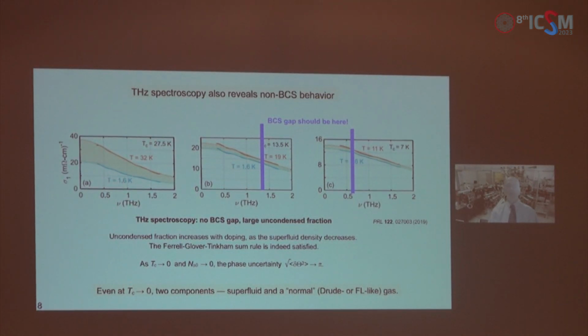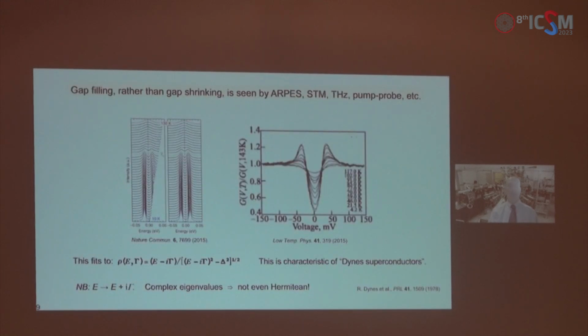In overdoped cuprates, as temperature goes towards 0, only a fraction of carriers is in the superfluid. And this fraction F can be as small as just a few percent of the total carrier density. And the remaining 1 minus F electrons behave more or less Fermi-like and do not seem to participate in superconductivity at all.